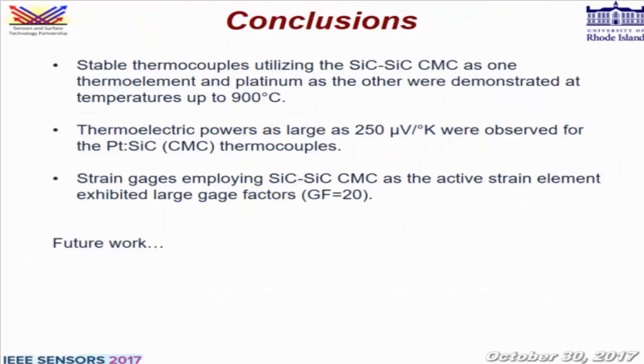Just to conclude, we were able to make these sensors successfully. The thermocouples performed well at about 900 degrees Celsius, but we need to get them to 1000. They were also able to produce thermoelectric voltages of around 250, which is pretty high. The higher it is, the higher the resolution of your reading. Same with the strain gauges. We got gauge factors of around 20.